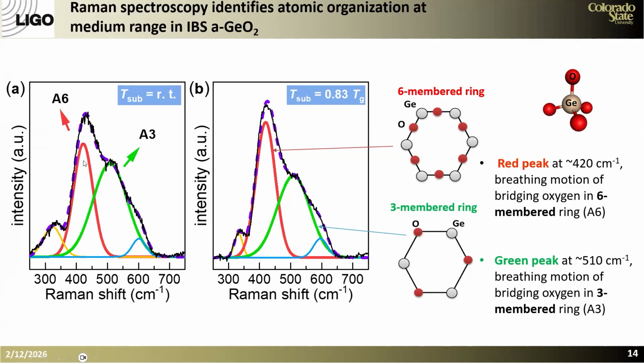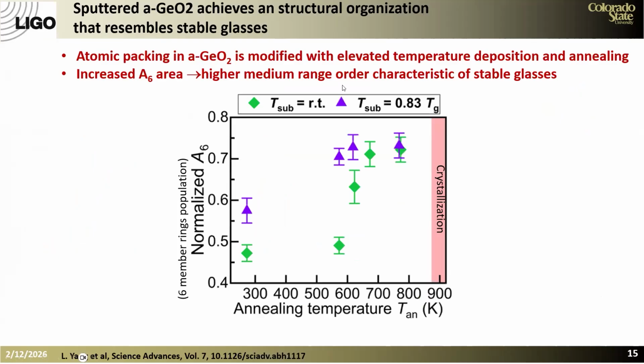And the Raman spectrum of germania has contributions mainly from 6-member rings. This is the red spectrum, and 3-member rings. And this is the green line here. So the black is what we measured in Raman. Then what we found is that if we deposit at higher temperature, you see that the intensity of the red peak increases compared to the intensity of the green peak. And that indicates that indeed the material has now a larger proportion of large rings.